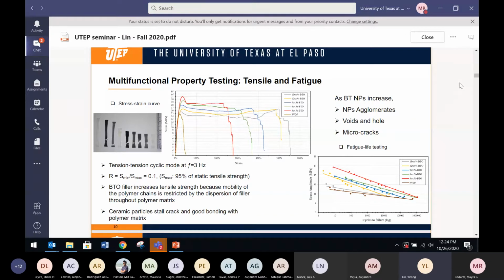So you can not only make a material self-sensing, but at the same time you can make it tougher, right? The reason is that these nanoparticles are linking to the polymers, so it's kind of an interlocking process. It's making the polymer tougher. We also did dynamic testing that you see over here. PVDF has a low dynamic failure stress, but once you add these particles, it can also increase its dynamic failure strength. So that's good. Basically, one stone, two birds, right? Not only do you get sensing, at the same time you increase mechanical properties. Next slide.